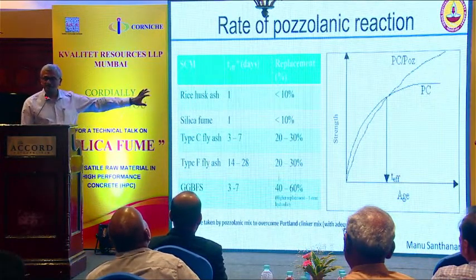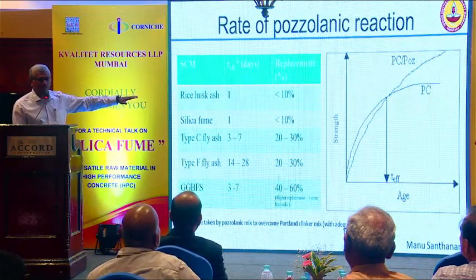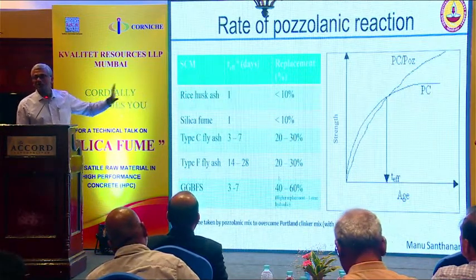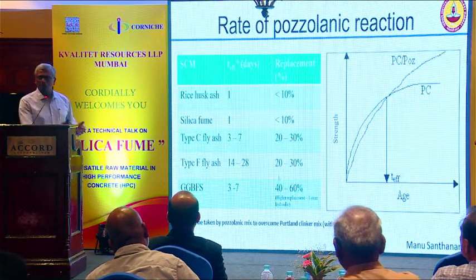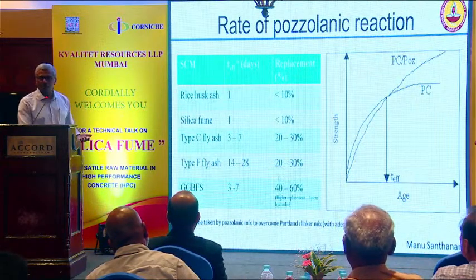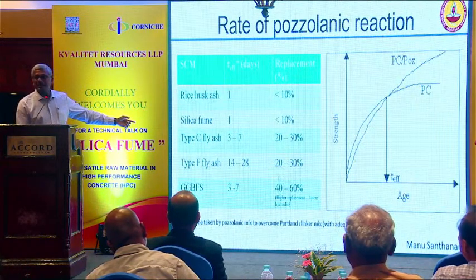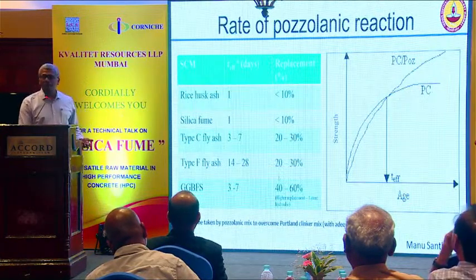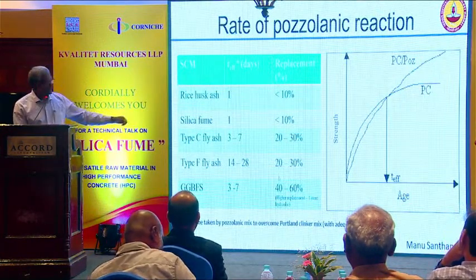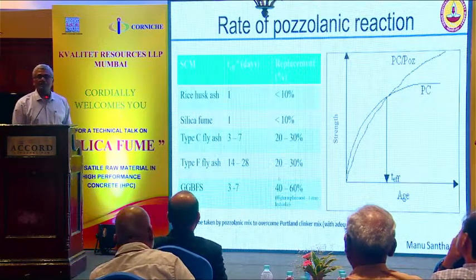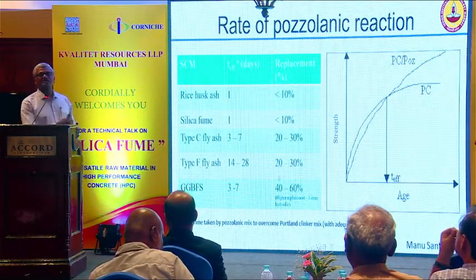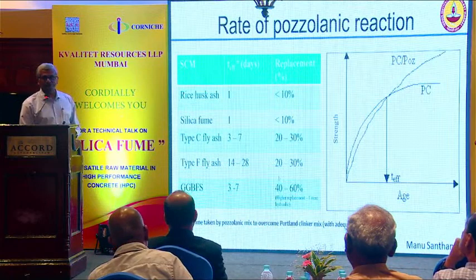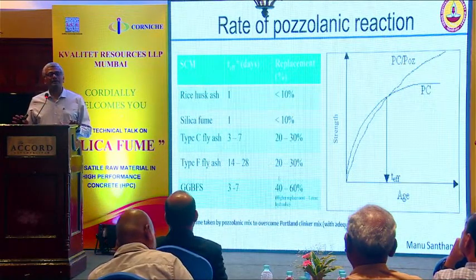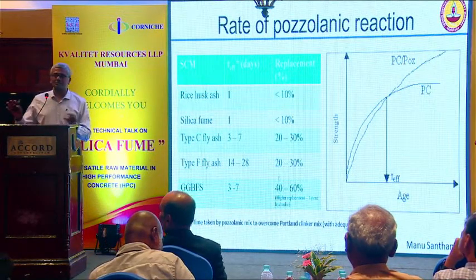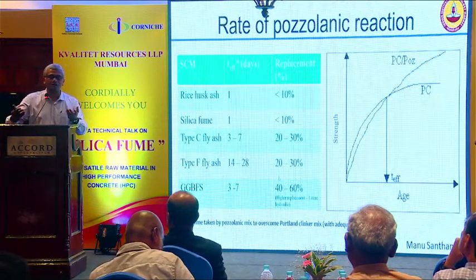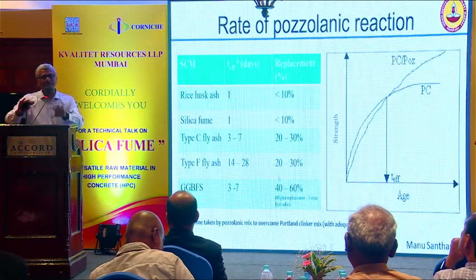But here we are sure about the kind of replacement we are doing. It's restricted to about 10%. We'll talk about why that happens and why you can't put much more than that. In type C fly ash, which is the one which we get from Neyveli, for instance, it will take about 7 days for the mix with the fly ash to reach the strength equal to that of cement. Now here I'm talking about just replacing OPC with these materials. I'm not redesigning the concrete. Okay, I'm just replacing OPC.